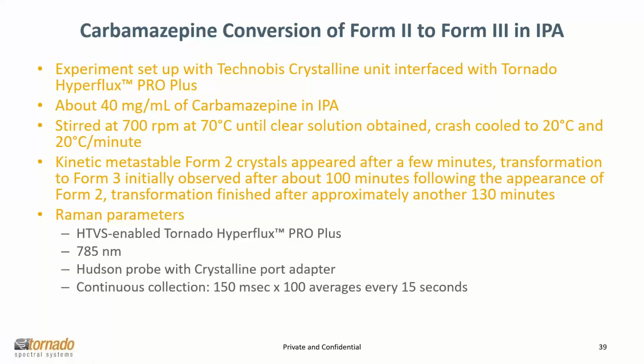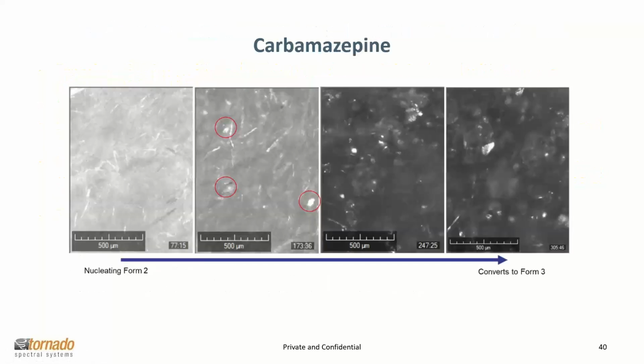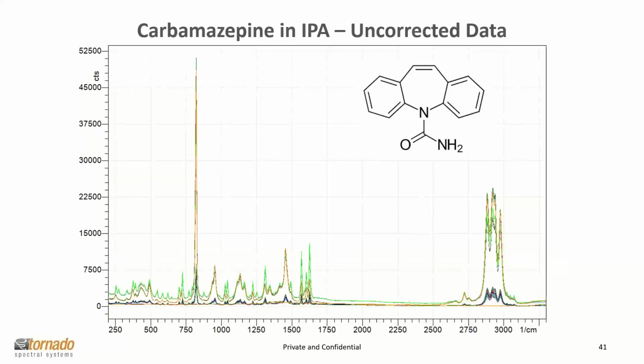And then the carbamazepine study, and again, I won't go into too much detail. Thomas already mentioned it's a much longer process than the mefenamic acid. So we were basically doing collections over 15 seconds to follow this particular process as it occurred. The pictures that were shared, this is shared in the application notes that we put out, of the needle-like crystals going to the block crystals.